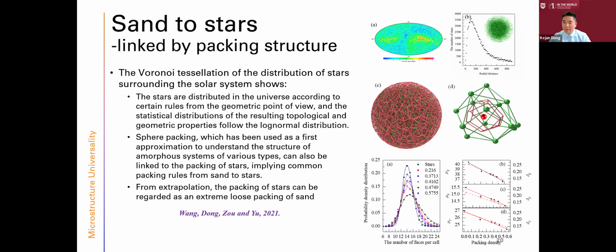And interestingly, what we find is here. If you look at this figure, this is the number of faces for the star or for the particles. So only this curve is the distribution of the number of faces per Voronoi cell for the stars, and these ones are the packing of sand of different packing fractions. If I don't tell you they have different data, one from stars and the other from sand, you may say that looks like the same system. So if we check other parameters like the mean value and the standard deviation of the different Voronoi properties, we can also get a very consistent trend from the sand to the stars.